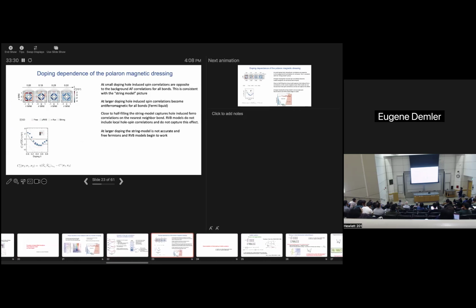And then one can look at an even more sophisticated correlation function. This is a three-point correlation function. Again, it's spin as a function of distance to the hole. Let me not go through all of the details, but just want to emphasize. These are experimental results as a function of doping, but then we can compare them to different theories. And there is one theory which we already discussed. This is the geometrical string, and we see that it's actually not so bad at small doping, close to half filling. Particularly it shows the change of sign, but then it doesn't work for larger doping.